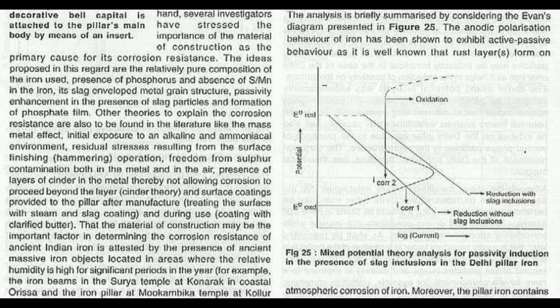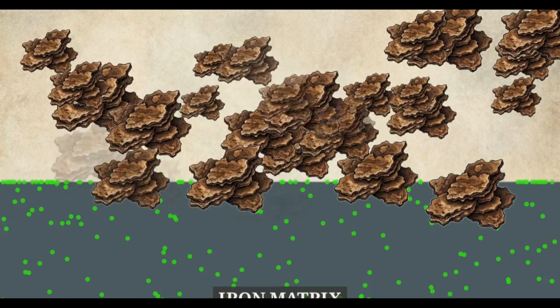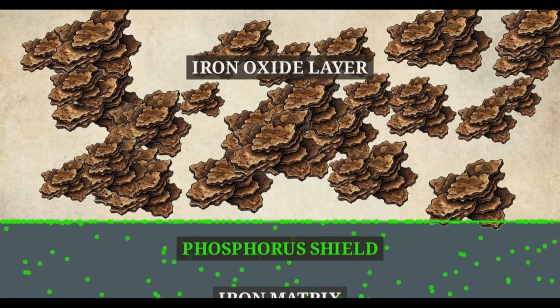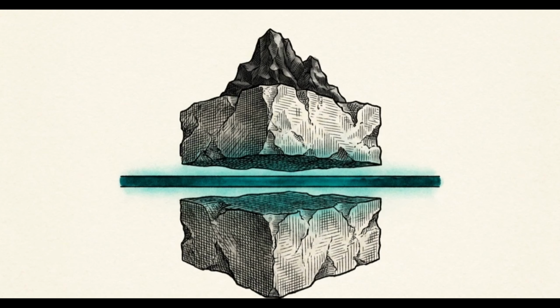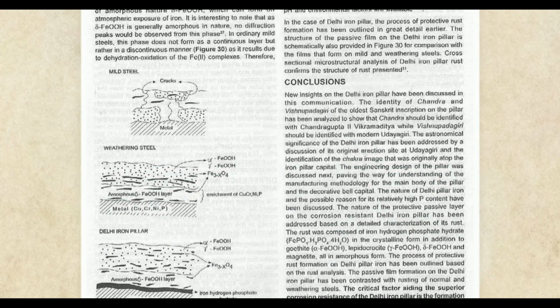The corrosion current shifts from I corr 1 to a significantly higher I corr 2, showing the pillar initially corroded much faster than modern mild steel. This rapid initial dissolution forced a massive concentration of phosphorus to accumulate at the boundary between the metal and the oxide layer. The entrapped slag acted as a sacrificial engine, rapidly rusting away the surface iron to concentrate the critical phosphorus shield beneath it. These cross-sections compare the rust structures.